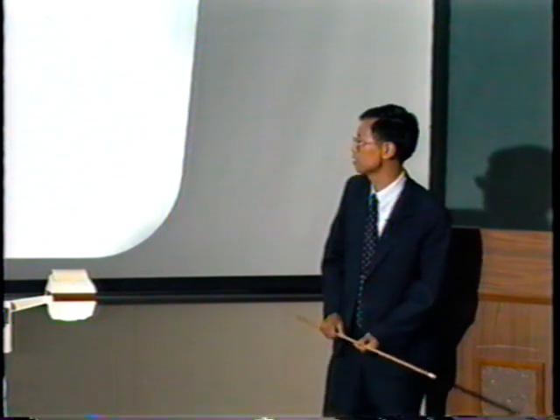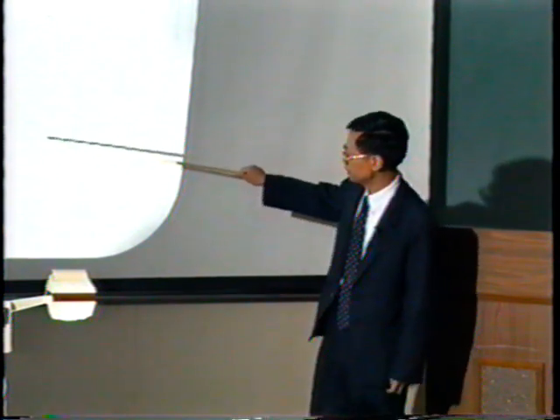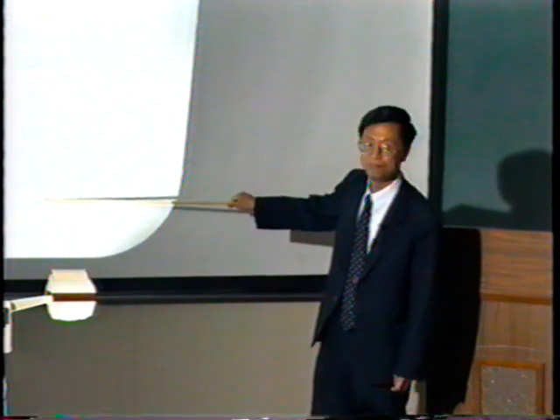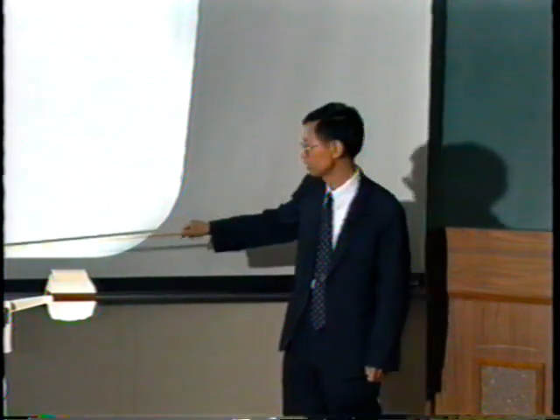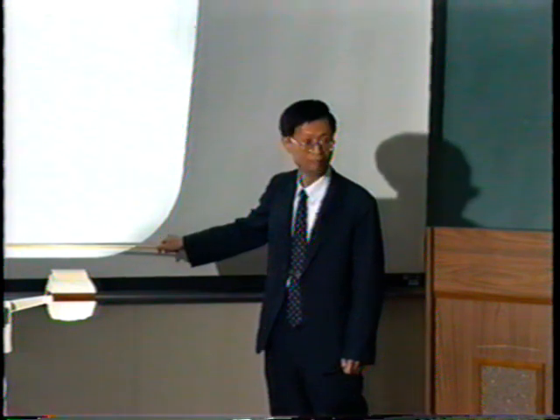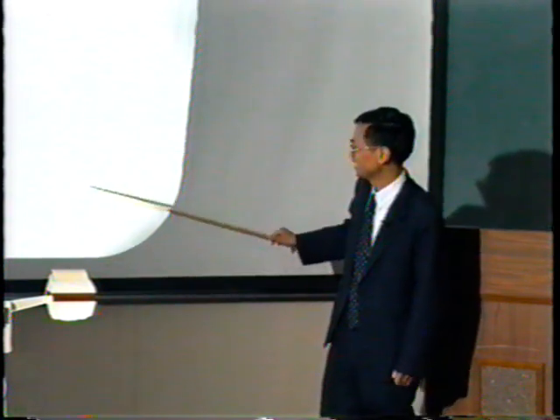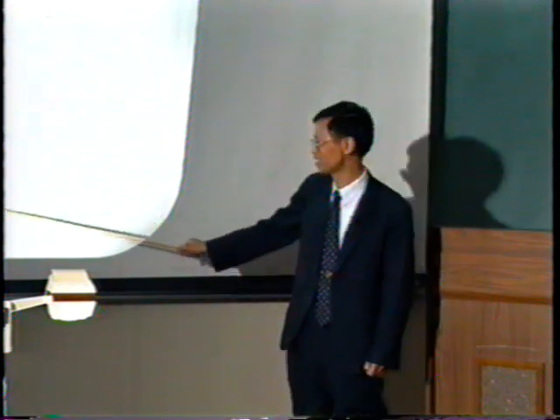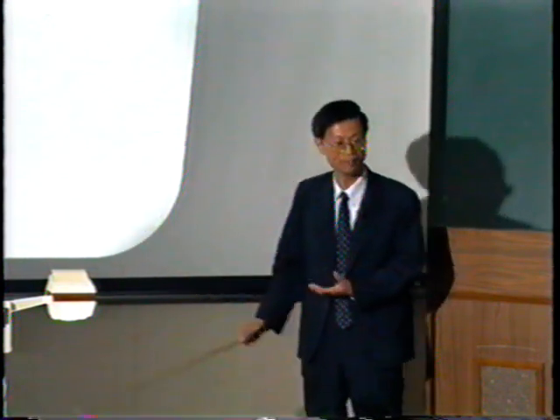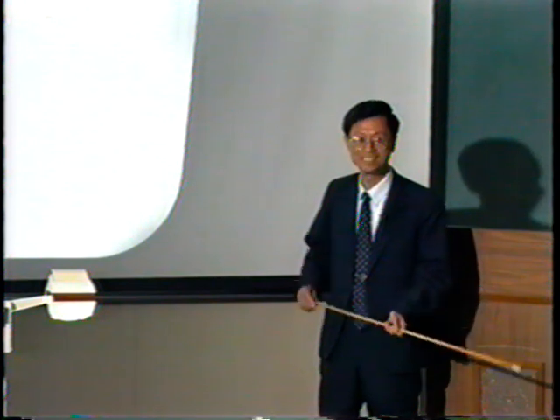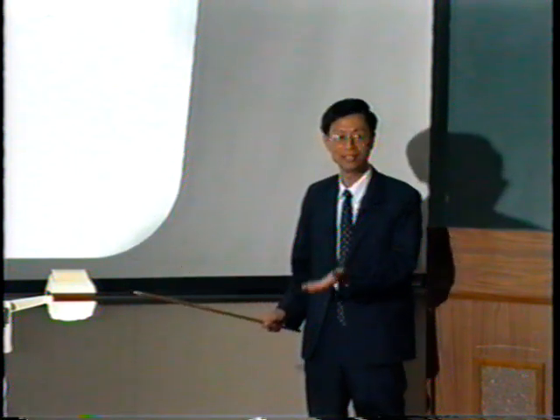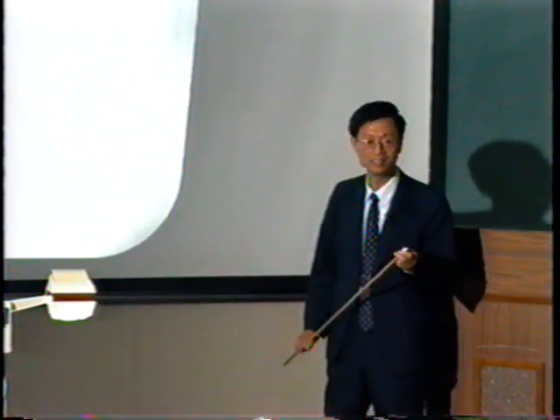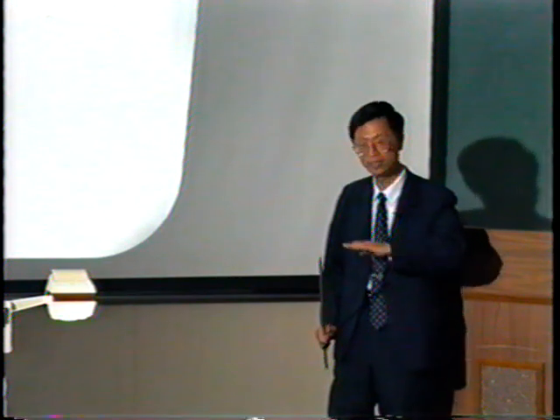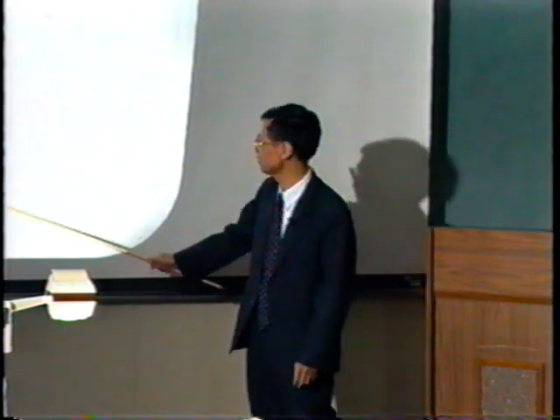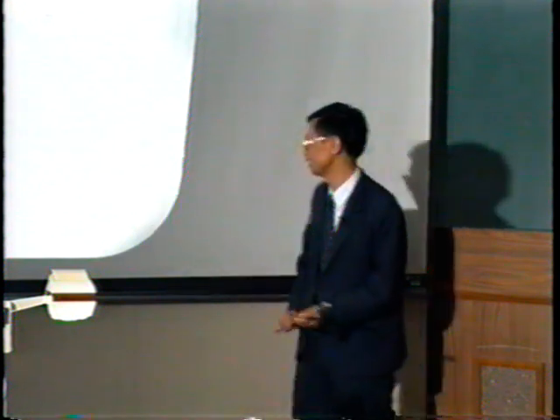The general conclusion is that the heat, the cooling, the discharge have no big effect on this loading ratio. It's unexpected, because at the Nagoya conference we expected discharge would have a big effect on this kind of anomaly. And I was a hot fusion person at MIT. They use discharge to clean the wall and obtain record density confinement time, because discharge will clean the wall. So I guessed the discharge would have an effect on this loading, but it didn't.